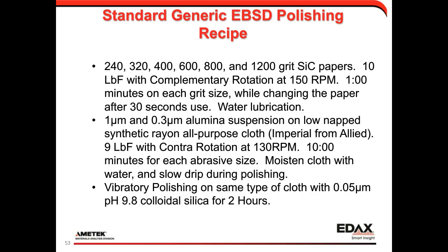So at this stage, I really just wanted to summarize what I've called my generic EBSD polishing recipe. Again, I start with 240 grit, step through 320, 400, 600, 800, 1200, at 10 pounds force. Here I use complementary rotation. What that means is both the platen and the samples are rotating in the same direction at 150 RPM.